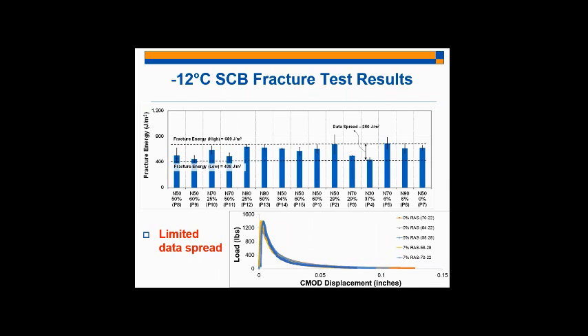So we have a variety of mixtures ranging from 0% asphalt binder replacement to, you can see here, 60% asphalt binder replacement. And the data spread, the range of fracture energy values extracted from these tests, is approximately 250 joules per meter squared. So this is a very limited spread of data. These are very different mixtures. You can tell simply by looking at the asphalt binder replacement values. Some of them have no recycled content whatsoever.